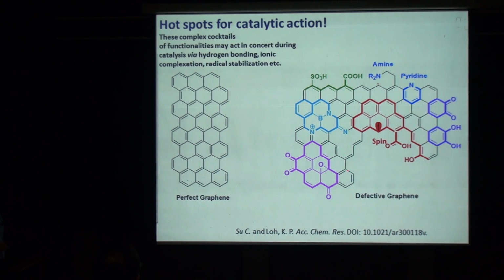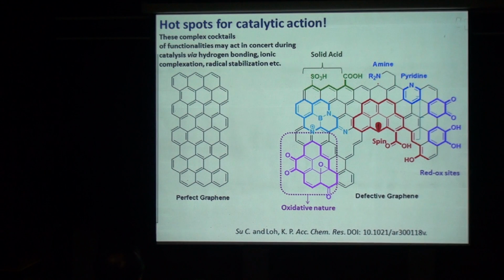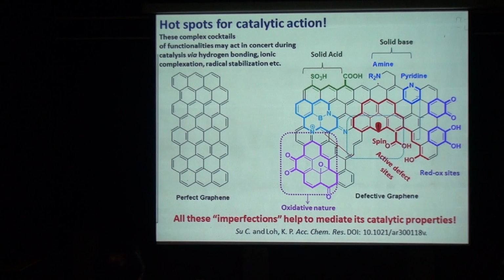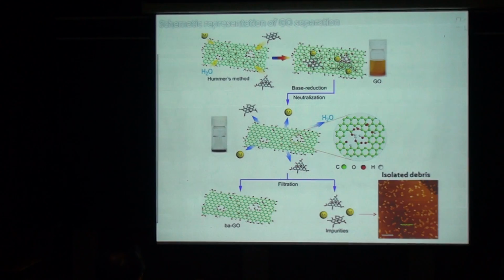We call this the diketone. It can be used in the oxidative dehydrogenation of ethylbenzene to form styrene, which is very important for forming plastic and so on. You can also introduce nitrogen groups, things like that. Sometimes you generate some unpaired spin, which gives rise to the possibility of a spin flip process in catalytic reaction. All kinds of strange things are possible. There's also solid acid possible if you introduce this sort of functional group, and all these oxygen groups can be oxidative in nature, and then you have redox active sites because you can perform redox exchange. All these imperfections help to mediate its catalytic properties. This is the key message.